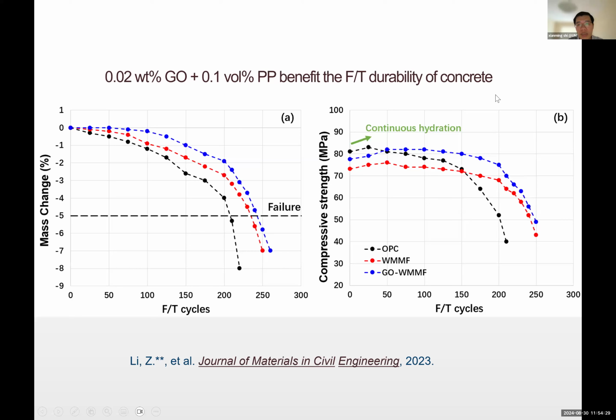Now, we also look at how it does in terms of freeze-thaw durability. You can see the dosage was 0.02% graphene oxide by weight of the cement, and the polypropylene microfiber, which is recycled from masks, is only 0.1% by volume of the concrete. The graph on the left shows mass loss. The graph on the right shows compressive strength loss over the number of rapid freeze-thaw cycles. And in general, these kinds of fibers help reduce the freeze-thaw damage.